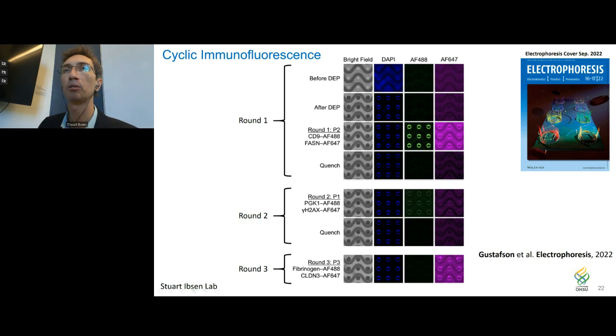And then we have two fluorescence channels, one in green and one in red, that allows us to look at two different biomarkers simultaneously on these collected particles. So this first row here, we can see that dielectrophoresis collected particles from the human plasma sample. We come in with our first round of staining to look for CD9 and FASN. We see that we get good signals from both of those.